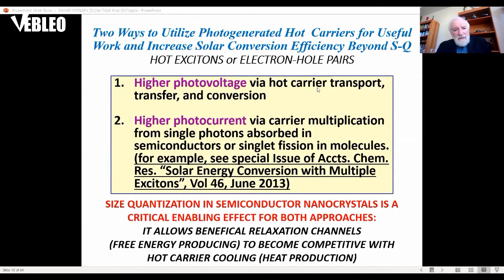If you can do that before they cool, then you will have a higher photovoltage above the voltage generally determined by the band gap when they cool to the band edges. Or secondly, there's a process called carrier multiplication, where you can use the excess energy if it's at least twice the band gap, or in the case of molecules, twice the S0 to S1 transition, to make two triplets. That process in molecules is called singlet fission, but in bulk semiconductors it's called multiple exciton generation.